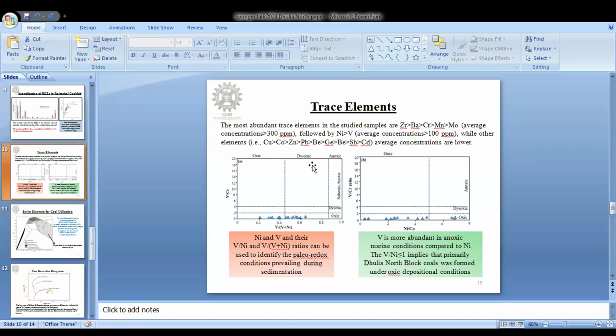So zirconium, as you can understand, the presence of zirconium tells us why this particular coal block is REE enriched, because zircon is one of the most prominent hosts of rare earth elements. So that is ZrSiO4. So that's zircon, the main element is zirconium, and that is already in abundance in this coal block, which is more than 300 ppm.